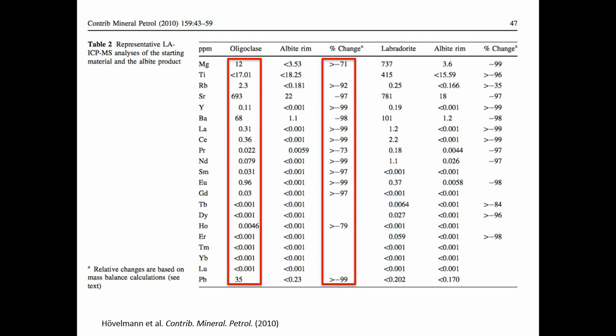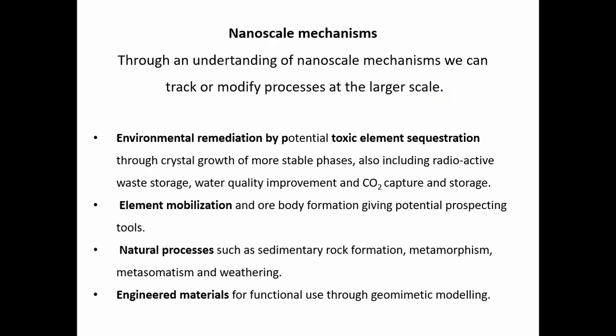Where are they? We have also shown through oxygen 18 that the oxygen ends up in the silica and aluminum oxide tetrahedra, and the only way that you can do that is to break all bonds. If the oxygen 18 is going to end up in the new structure, at that interface, we've got complete dissolution followed by reprecipitation of the new phase. And all of those elements that were originally present are now in solution at the interface, ready to be transported somewhere else by diffusion through the fluid phase, and when conditions change, chemically or physically, they may be deposited somewhere else. So this is the basis of ore formation, that from elements that were originally,